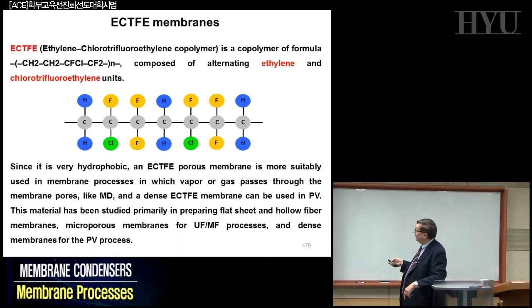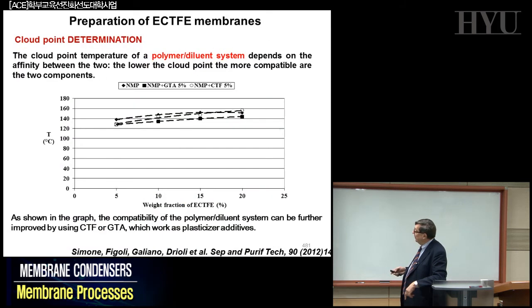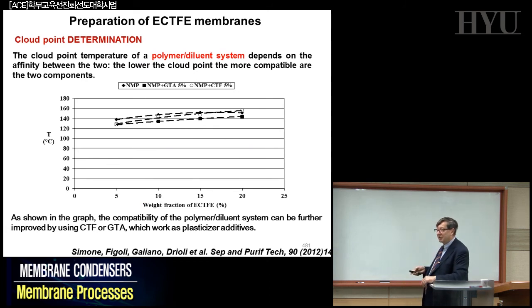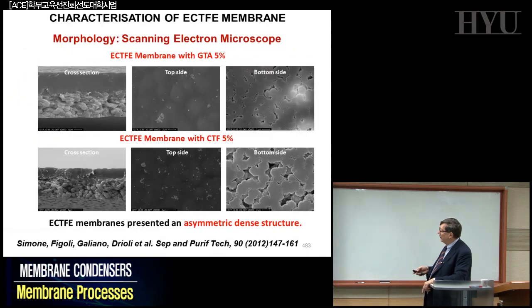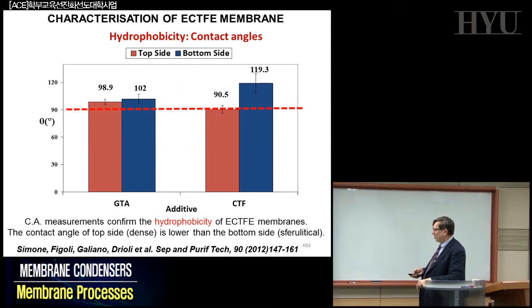So you have to operate in a situation in which everything is TIPS, and again, you have to start to measure your cloud point temperature of the polymer diluent system, and try to understand how the system works. And when you know this, you can realize, interestingly, quite different morphology, going from a dense skin on the one side to a very porous skin on the bottom side, and that is a question of the different temperature you are working at. And that is the level of hydrophobic character, the contact angle.